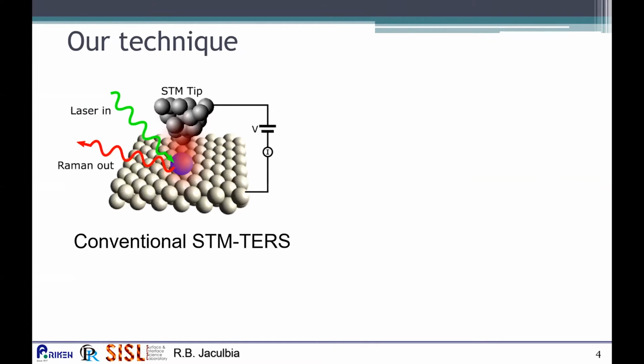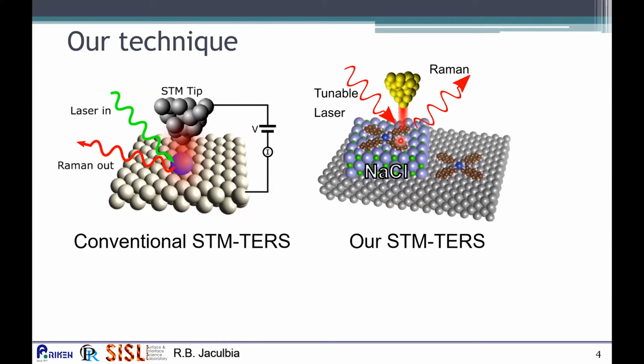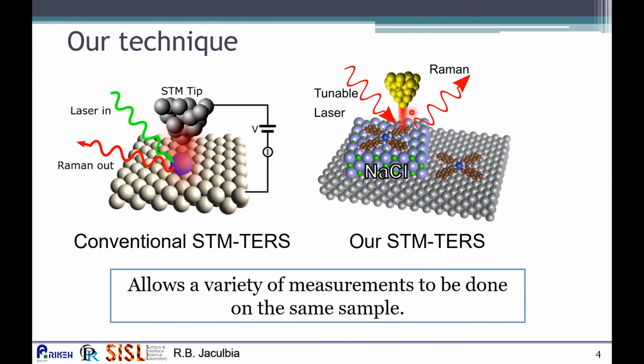For conventional STM-based TERS measurements, the molecule is placed directly on a metal surface. However, the interaction between the molecule and the metal surface complicates the analysis of such a system. So in order to avoid this problem, in our work, we utilize a sodium chloride surface which acts as a decoupling layer in order to physically separate the target molecule and the metal surface, and then we can perform STM TERS. Moreover, aside from STM TERS, a variety of measurements can also be applied on the same sample, apart from just Raman spectroscopy.